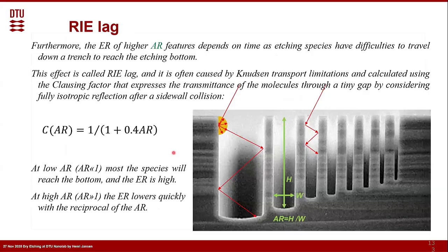Then a second thing I would like to add a little bit, because it comes back also in the second part of this, is that the etch rate depends on the aspect ratio of features. That means here you have a cross section where you see after a certain time of etching that structures are etching deeper into the silicon.